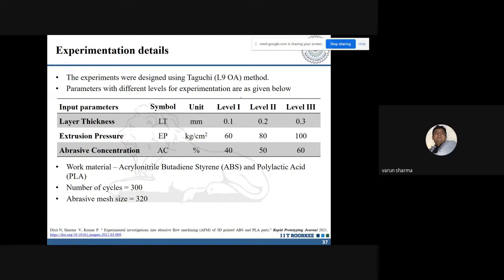Now, the layer thickness that we moved was from 0.1 to 0.2 to 0.3. For 0.3, there was more staircase effect. For 0.1, there was less staircase effect. So, if the workpiece that I am going to finish has a higher staircase effect at the initial level, the percentage improvement in the surface finish will also be on a higher side. The extrusion pressure, we varied from 60 to 100.